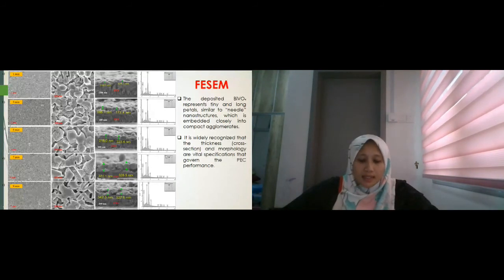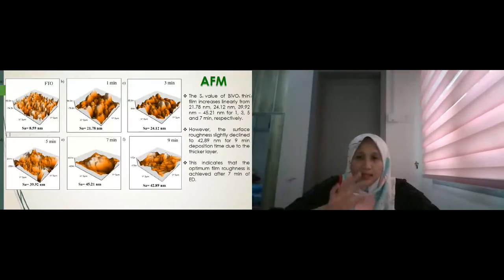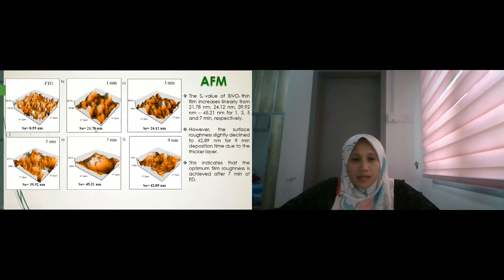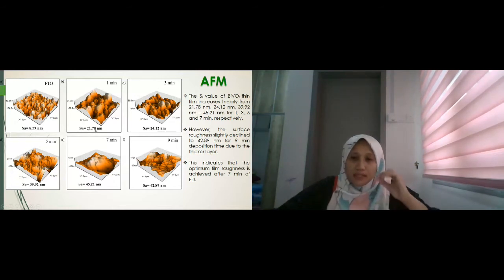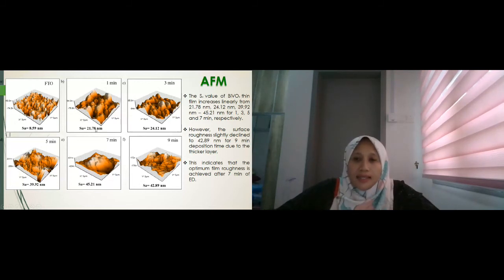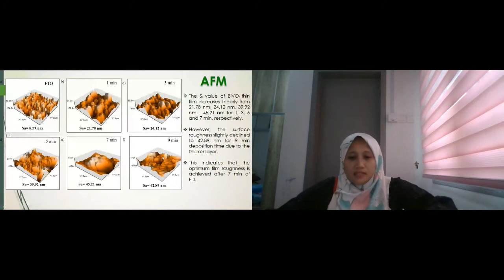Okay, this is to check the roughness of our photoanode, which is bismuth vanadate, and we use atomic force microscopy. Here, I use the FTO, which means the substrate is a conductive material, as a comparison to my photoanode at 1 minute, 3 minutes, 5 minutes until 9 minutes. The roughness value of our photoanode increases from 21 nanometer until 45.21 nanometer, but however, the surface roughness slightly declines to around 42.89 nanometer at 9 minutes deposition because of the thicker layer. So this indicates that the optimum film roughness is achieved after 7 minutes of deposition.